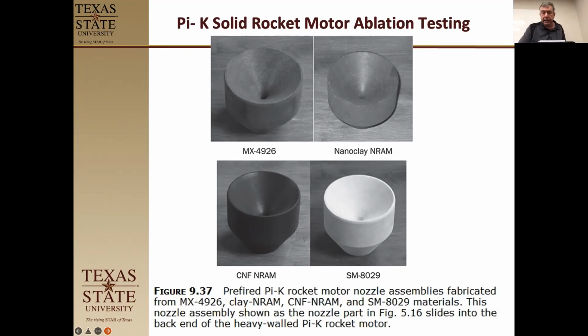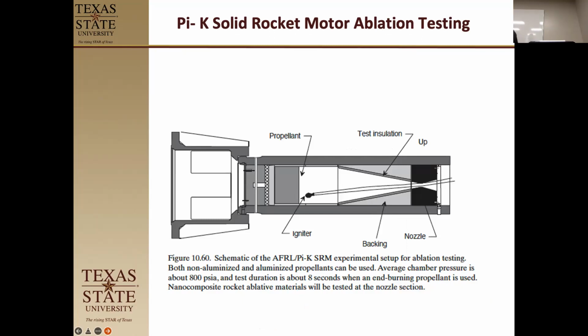So when they tested that, they use this kind of test bed right here. Most of the machine is just built as is. You have some test equipment here. You put a plug of propellant here, you can ignite it. If you're testing insulation, you put the insulation here, and you back it with another piece of metal or foam. If you're testing the nozzle, you put the nozzle here, and then you burn for a consistent test. It's usually about 8 seconds. It generates about 800 psi in the chamber, and then as soon as it comes out that nozzle,